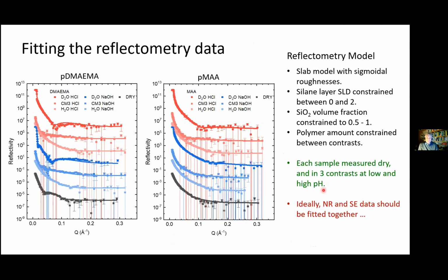Now here, ideally, we would like to fit the neutron and ellipsometry parts together. But there is an inherent difficulty here, because we are using these 2 different methods because they are good and effective in different ranges, basically different thickness ranges. And this should really be taken into account. Basically the data should be weighed differently on different length scales. So this is a non-trivial problem which we haven't really solved yet.